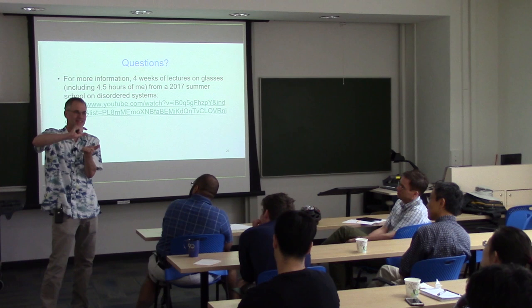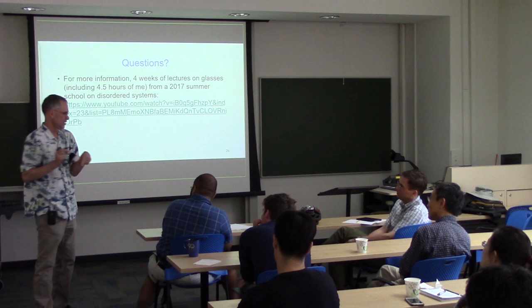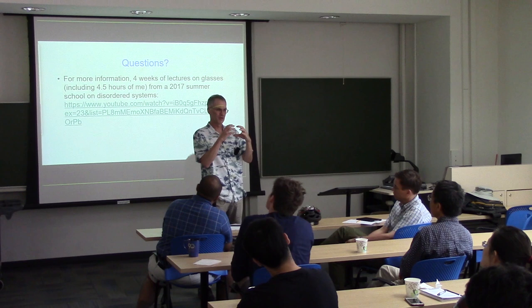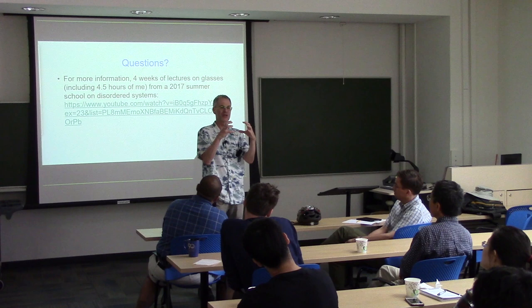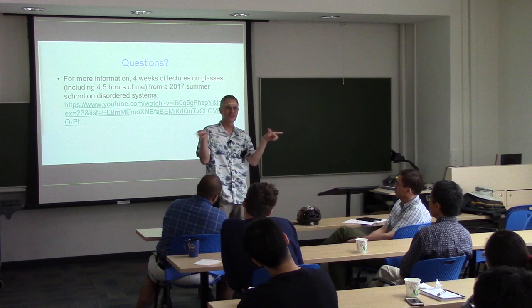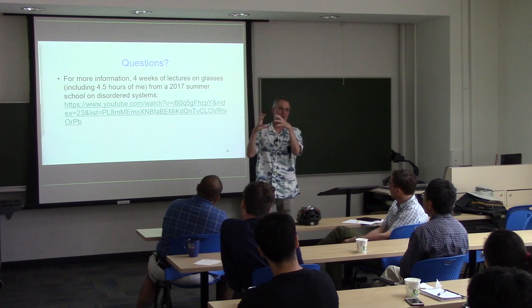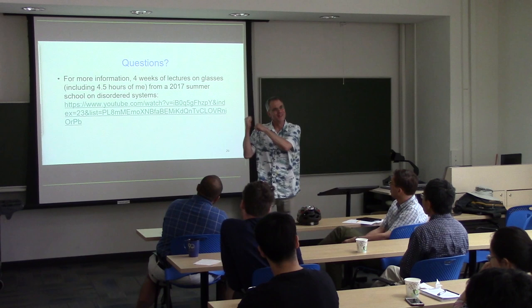These layers were made by vapor deposition. And then they tracked down the reason. In OLEDs, there's an organic molecule, and there's an electron and a hole that recombine on the molecule. The molecule emits light, either fluorescence or phosphorescence. They found that if you pack a glass densely around this emitter molecule, the quantum yield of the molecule goes up because you cut off radiationless relaxation pathways. So it's similar to eliminating these secondary relaxation processes. You're limiting the kinds of motions that occur in the glass, and for that particular application, having a glass without motion is better.